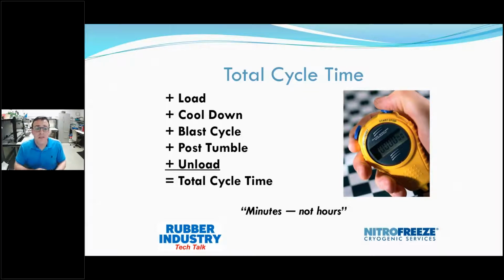So the post-tumble is simply now the media has stopped blasting, but the basket's still going. And the whole point of that is at that point, gaseous nitrogen is shot in with compressed air as well to remove any residual flash left on the parts and to remove any residual media that might be in the basket. And then we have unload, and that's simply taking the basket, opening the door, taking the basket out of the machine, and putting the parts into a work holder of some sort so that they can be brought back to ambient temperature. That's your total cycle time.